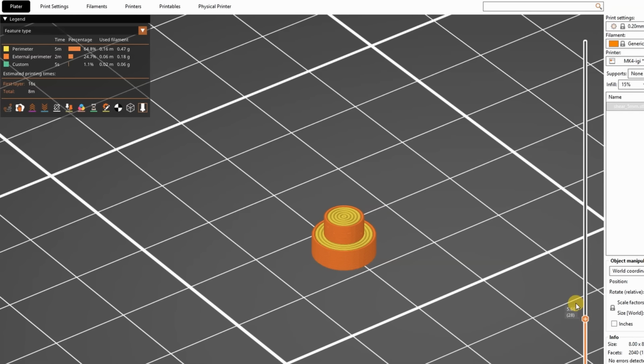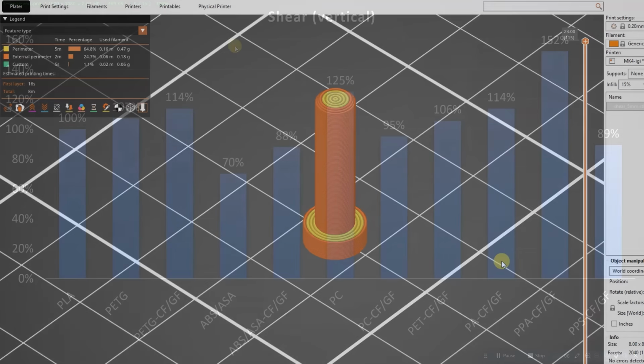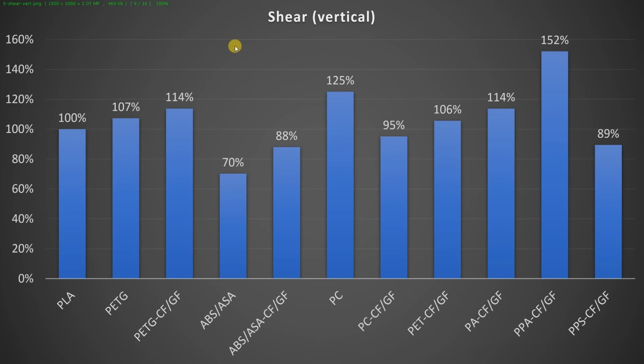Same two-sided shear test, but objects are printed in vertical position. I started this testing much later, but I have at least 50% of the measured data, so I believe that's enough for some relevant analyzing. From the basic filaments, we can see that again ABS ASA is significantly weaker, mostly because of that weaker layer adhesion. From other technical filaments, we can see big differences, deviation, but still by far the strongest is PPA-CF.